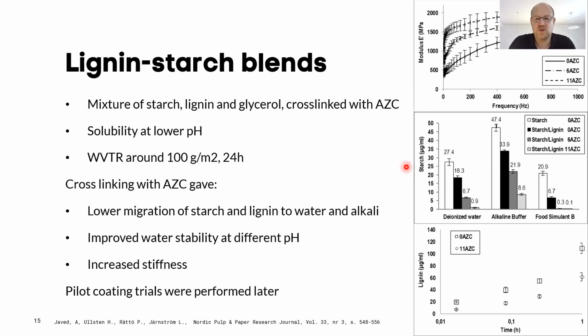What we also could see was that we had a better chemical stability of the material itself when we looked at how much starch would actually be dissolved in deionized water, alkaline buffer, or food simulant. You could see that if you mix with lignin, you have less starch going out, and if you cross-link it, it's even more stable, and that's especially significant for the food simulant here. We could also see that we had less lignin being extracted from the material when we put it in alkali or in acid too. So we could draw the conclusion that we had better stability here.